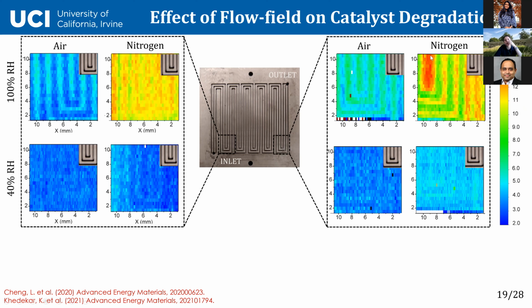Why? Well, we think it's because under land locations, the catalyst is cooler. Why? Because lands are made out of graphite, while in channels you have just gas flowing. So lands are able to remove heat faster. And then you have water condensation in the catalyst layer. And this condensation increases local hydration, and then platinum can move more freely. So we found that. We published two papers on this, so that was an interesting finding.